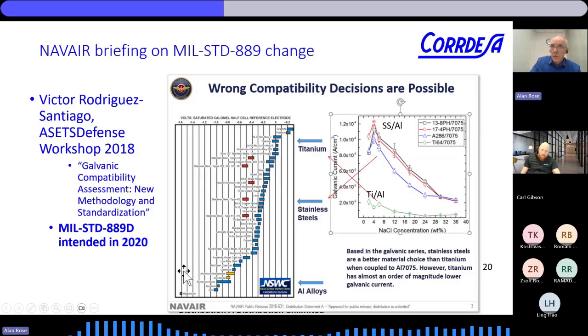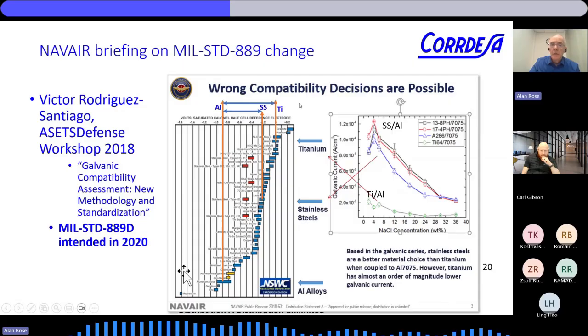And if you recall on that F18, the bushing material they were choosing was a stainless steel. Stainless steel, that's good. That won't rust. Let's do stainless steel. So stainless steel on its own, good. But if it's in a galvanic couple, it can end up being really bad. So if we look at aluminum on this potential chart, and we pick roughly where the stainless steels are, you go, oh, there's a potential difference. And then you say, okay, what if we want to use titanium for our fasteners? Oh, no, that's not a good idea. The potential difference is larger.